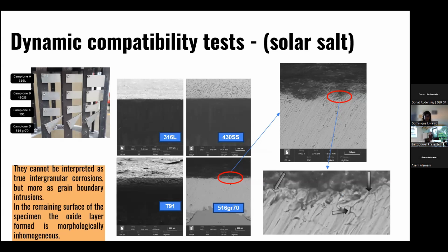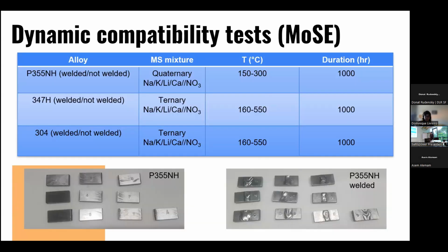We can see that there are some problems, some little holes that formed that cannot be interpreted as intergranular corrosion, but more as grain boundary intrusion over time that can lead to a very huge crack on the oxide layer, leading to the salt penetrating inside the steel.